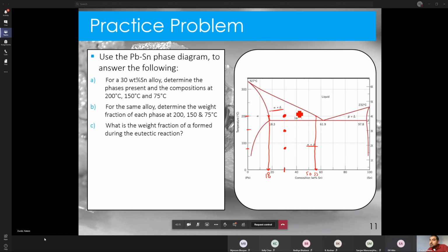So I just do one of the levers without thinking which phase I'm calculating. Then I ask myself, well, it looks like I'm closer to alpha, so what I calculated, the 32%, must be the liquid. Because the liquid is here, and I'm far away from the liquid, so I have less than 50% liquid. So the liquid will be 32%, and the alpha is actually the majority. It should be 68%, right? That adds up to 100.